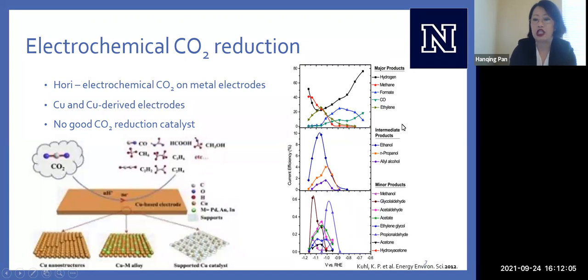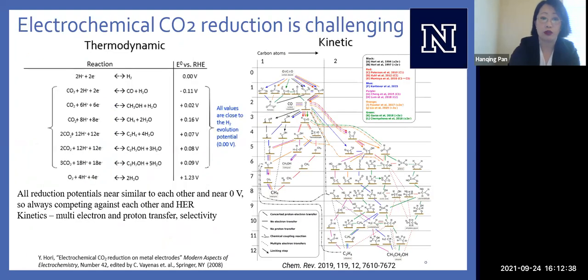And so that's the issue with selectivity. Can we steer toward one particular product without generating the others? And another metric that we use when we talk about CO2 reduction is Faradaic efficiency. And so that's how we quantify what goes in, what comes out, kind of like a percent yield. And Faradaic efficiency for a lot of these products, especially multi-carbon and oxygenated products, are still low. And so due to low Faradaic efficiencies, low selectivity, CO2 reduction is still pretty difficult to do.